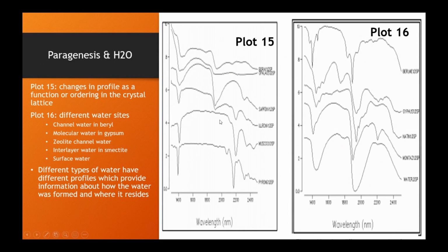So here in plot 15, this shows changes in profile as a function of ordering in the crystal lattice from broad, low-temperature smectites to high-temperature mica and pyrophyllite. We're looking at plot 16 here. This is showing different water sites from channel water in beryl to molecular water in gypsum to zeolite water, channel water, to interlayer water in smectites to surface water.